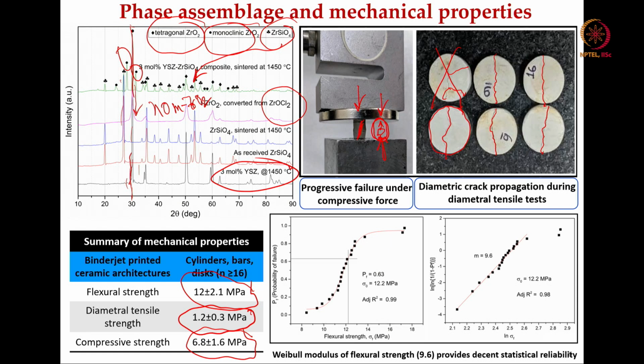As I mentioned, and as you would realize by now, this 3D binder jet printed zirconia also has a lot of porosity. So, this kind of porous binder jet 3D printed structure should also behave in a more brittle manner. What I was discussing is that binder jet 3D printed zirconia ceramic was equally porous like the binder jet 3D printed titanium 6 aluminum 4 vanadium. Therefore, the reliability in measuring the mechanical properties was emphasized, and we printed a large number of samples, and those samples were tested under different loading configurations, whether compression, flexure or diametral compression tests.